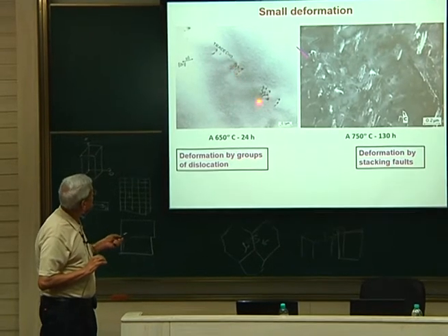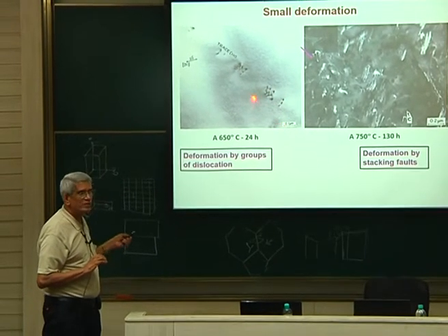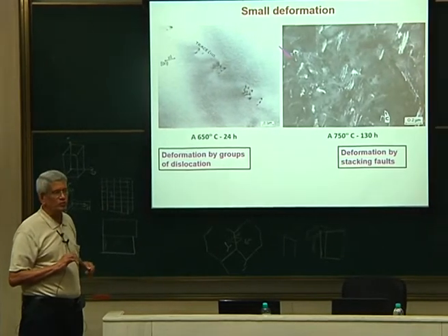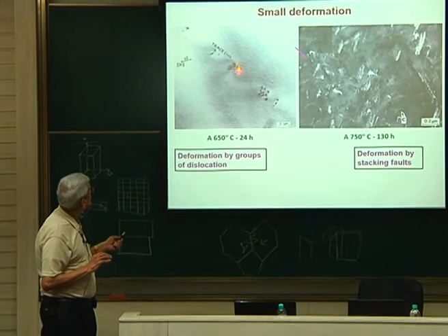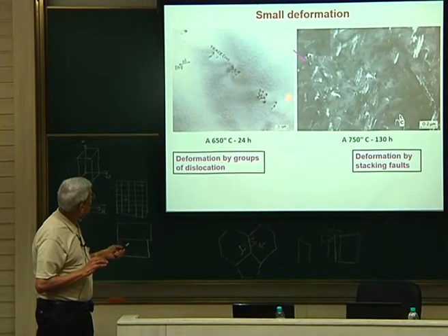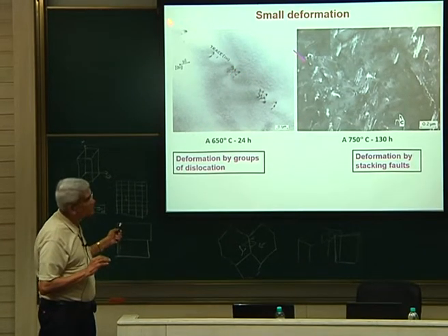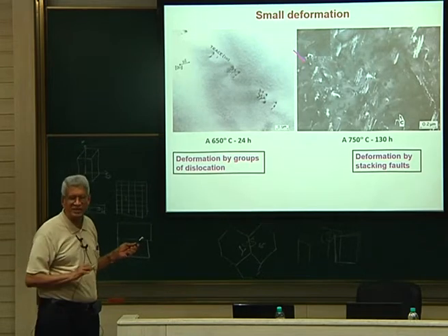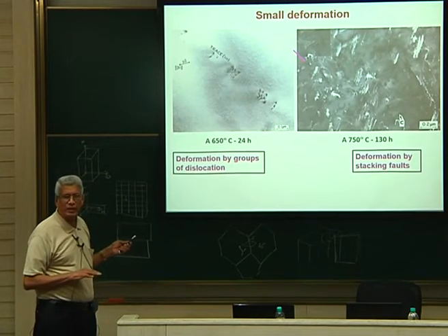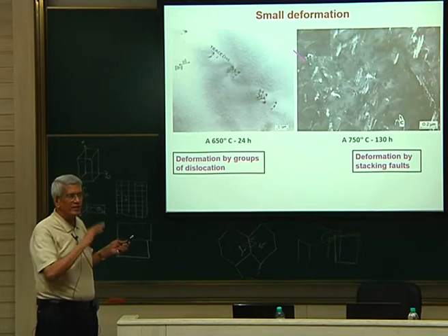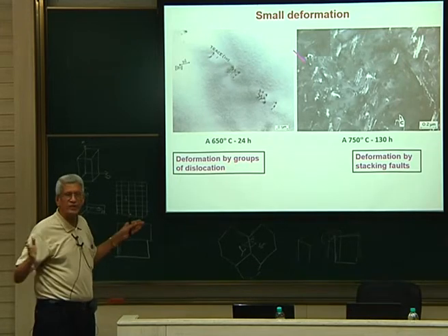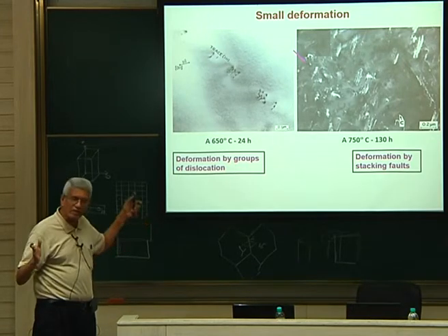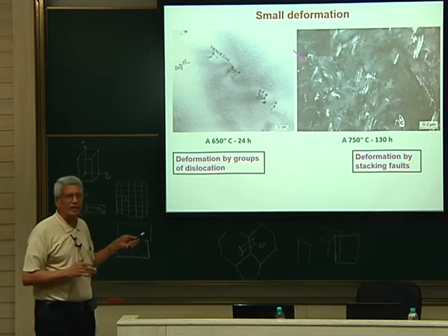Now, if you see here, there is a group of 4 dislocations which you can see, correct? Here you see 1, 2, 3, 4, here 1, 2, 3, 4. Afterwards, here also there is, then afterwards it gets reduced. There is a reason for that, which I will come to later. Essentially, what you can see is that in this particular alloy system, groups of 4 dislocations are passing through, bunched together like this. Otherwise, we see them randomly in a disordered material. That is not the way it happens in an ordered alloy.